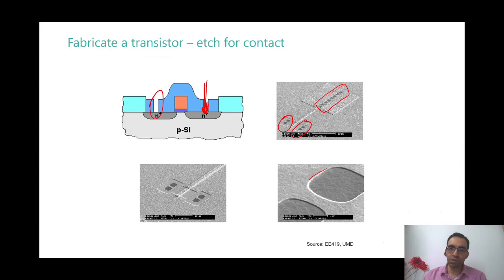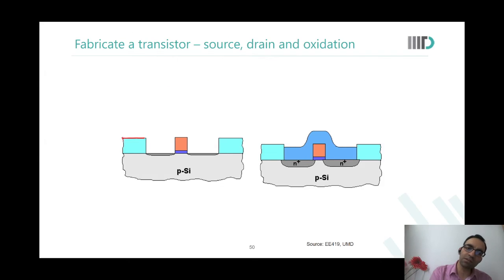Even if you look at the previous slides, see what happened. Do you think this oxide was always this thick? No. When you had fabricated the oxide, it would have been slightly wavy. You polished it. That is called CMP, chemomechanical planarization. You use chemicals and mechanical scrubbing to polish and planarize the surface, so you can planarize it a little more and have lesser thickness there. So you could change the duration to increase or decrease the thickness, and then CMP is the process through which you can finally arrive at the exact thickness that you needed.